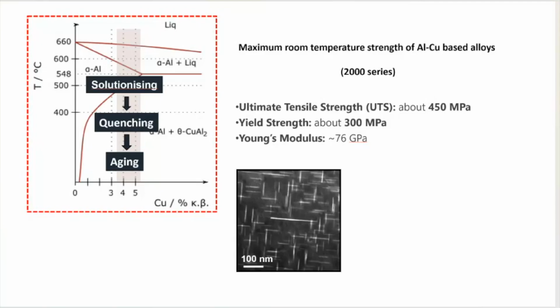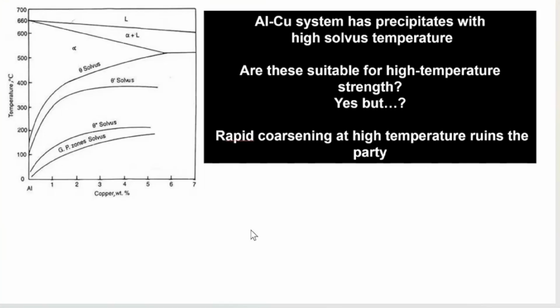In aluminum copper alloys, there are many precipitates, but all are plate shaped. As you see on the left-hand side, it is a metastable phase diagram. You can get GP zone, theta double prime, theta prime, and theta solvus with the increasing solvus temperature. Therefore, one should be able to get a high temperature strength in the aluminum alloys. But it does not happen.